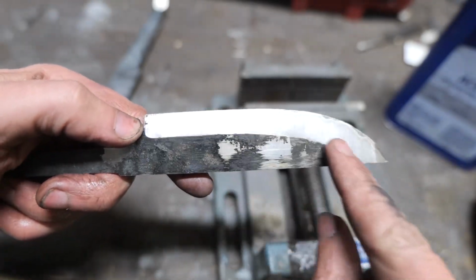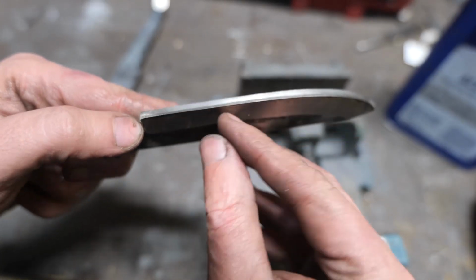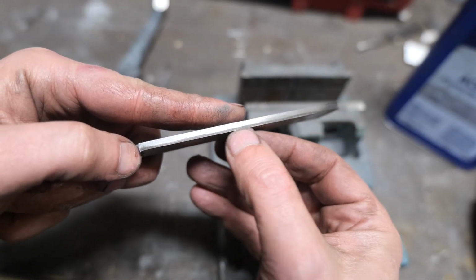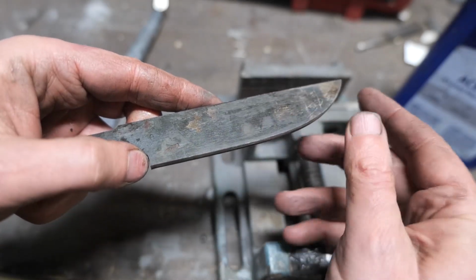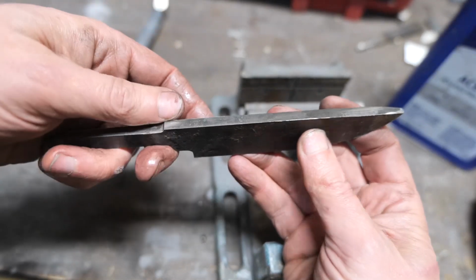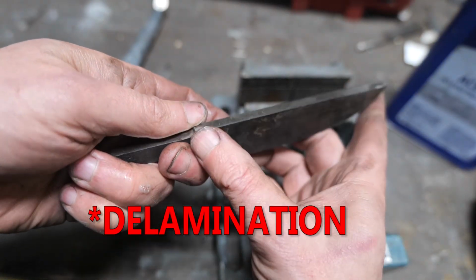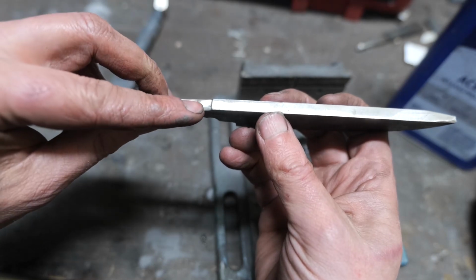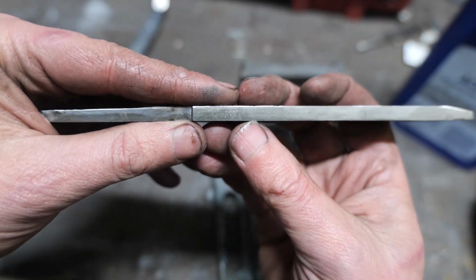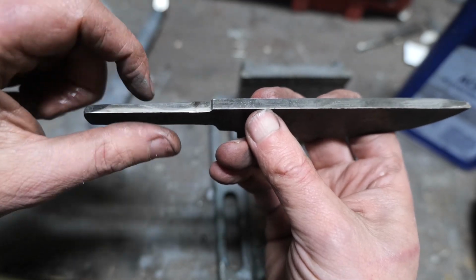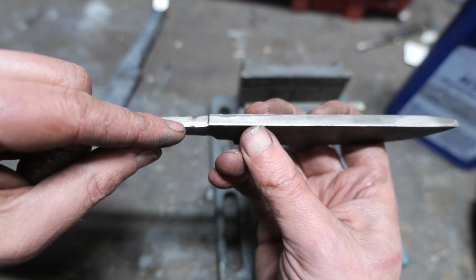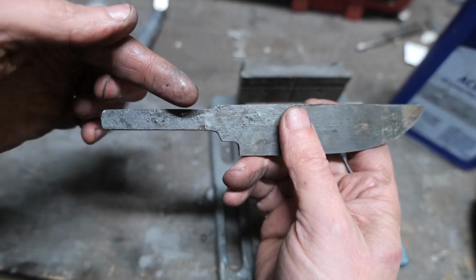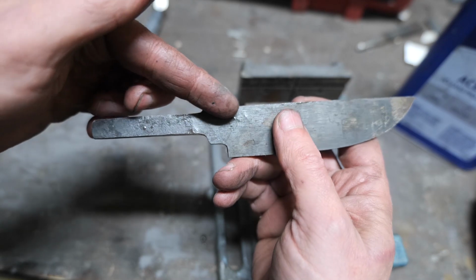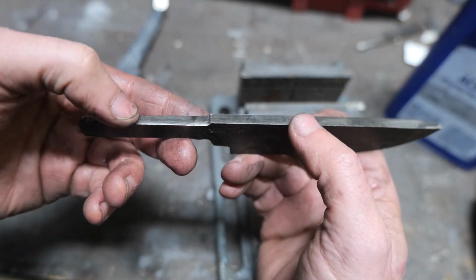Here it is. You can see I ground on this side and then etched it, and I'm just getting to the core there. You can sort of see the core there. See on this edge? And then I still have to grind on this side. But I had to come down this way because this right side started splitting right in here. I've finally ground it, and you can barely see it, but when it gets wet, or when fine dust starts collecting, a crack. You can see it's fine little splits right there and right there. It's almost gone. If I ground down another 2-3 millimeters here, it'd probably be gone. I just wouldn't have much knife left.